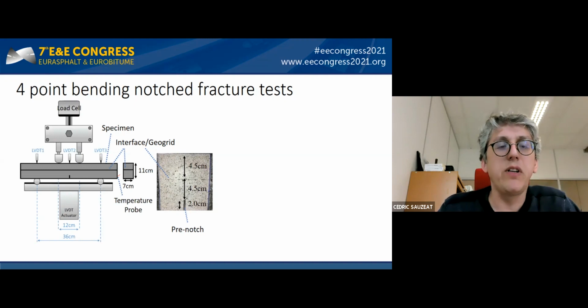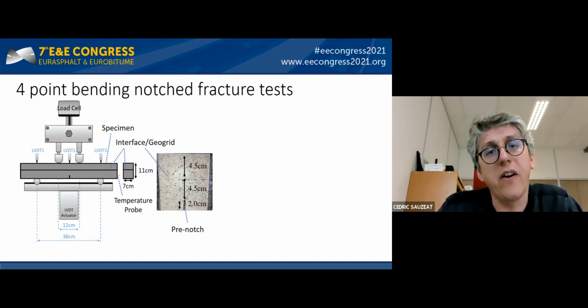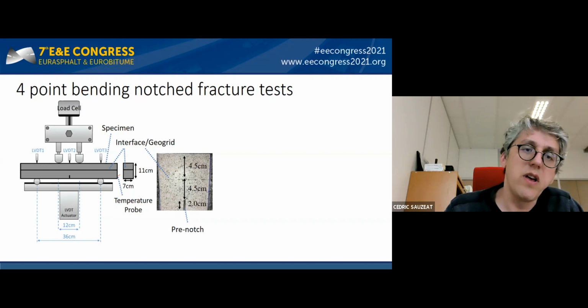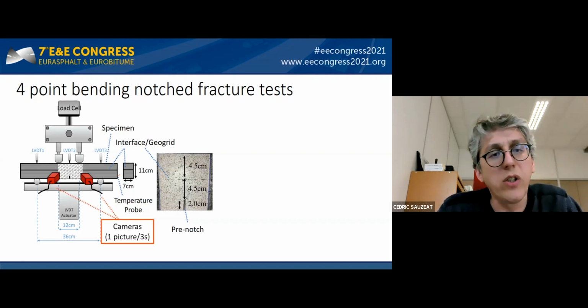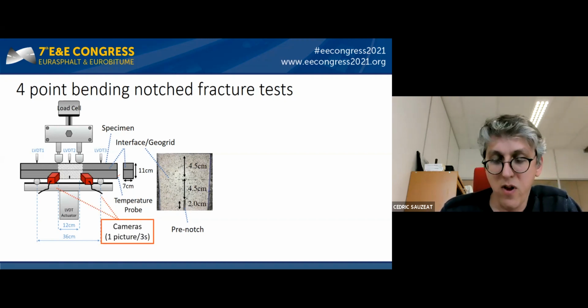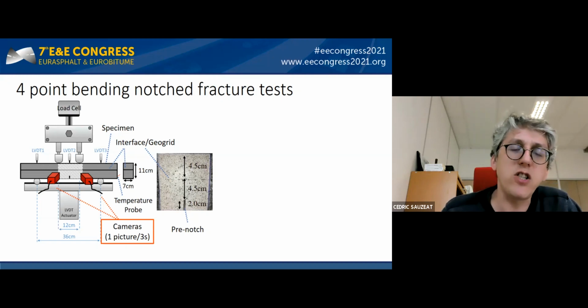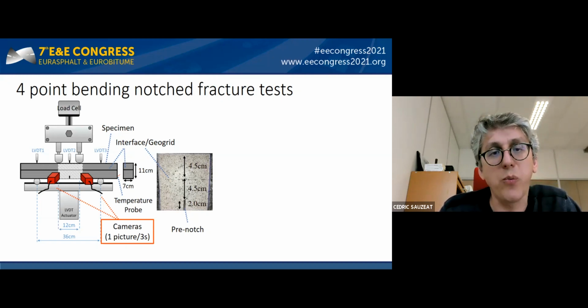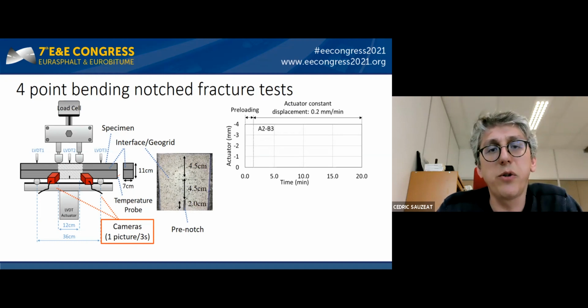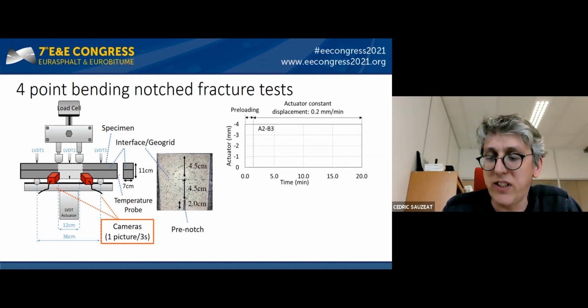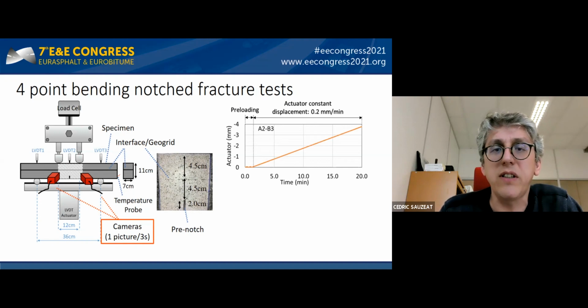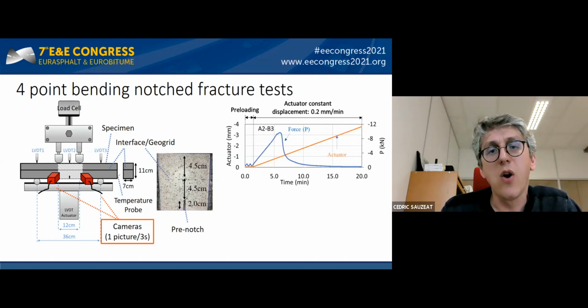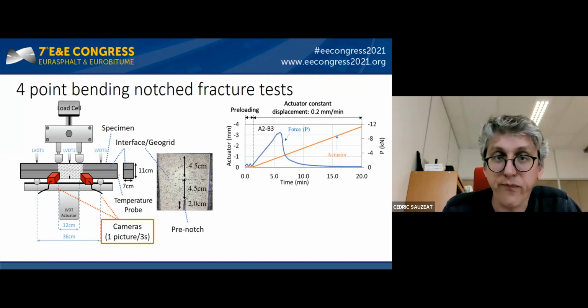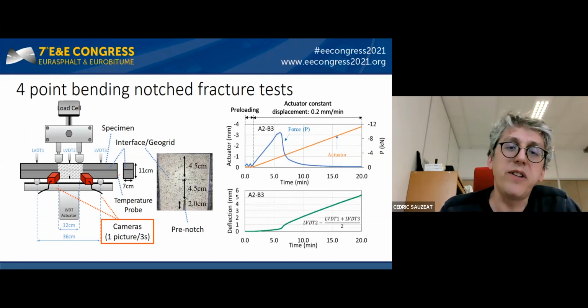These specimens were put in a 4-point bending test that we used. For this test, we also have cameras to perform digital image correlation. I will show you how we perform it after. So during the test, we apply a loading at a constant displacement rate. You can see here the displacement in function of time. We obtain the load in function of time also. And we can obtain the deflection from